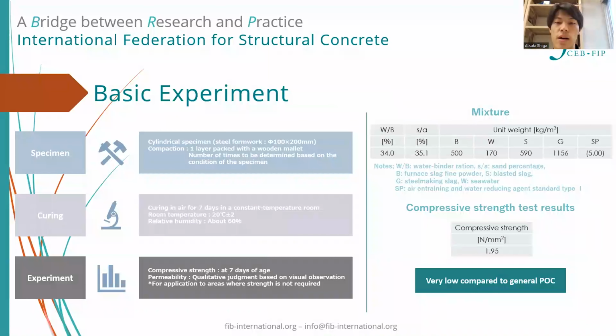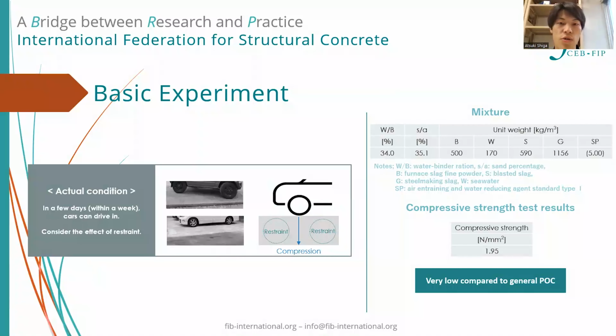Compressive strength was measured at 7 days of material age after air curing in a constant room temperature of 20 degrees and relative humidity of 60%, on the assumption that the pavement would be open after paving. The mixture determined by the experiment is shown here. The compressive strength of this mixture is 1.95 megapascal, which is very low compared to ordinary concrete. However, the actual paved concrete is expected to have higher strength than the experimental value, since people and light vehicles can pass through the concrete the day after it is placed.